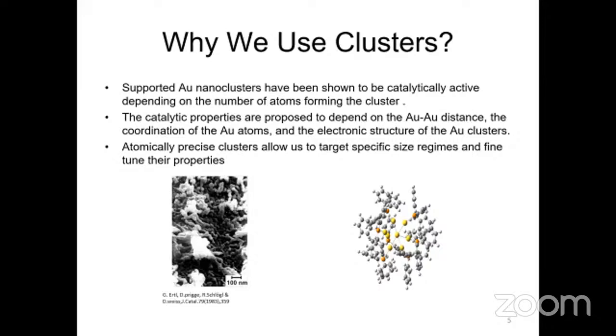Depending on the number of atoms inside the nanocluster, it can have different catalytic activities, like gold 9 is different from gold 8 and different from gold 11. But the previous literature used them in the gas phase, while to reach the demand of the industrial catalyst, we need to synthesize them chemically. This is the difference between what has been reported in the gas phase and what we produce here: the catalytic activities of the chemically synthesized cluster.